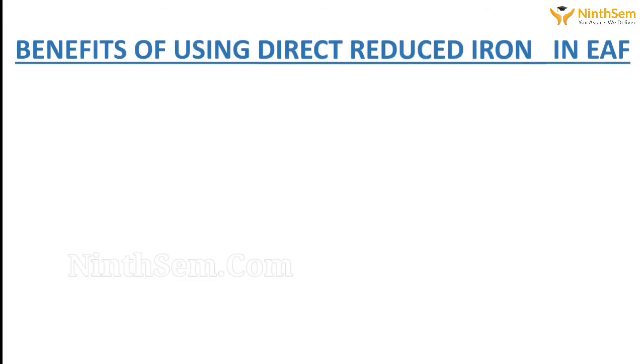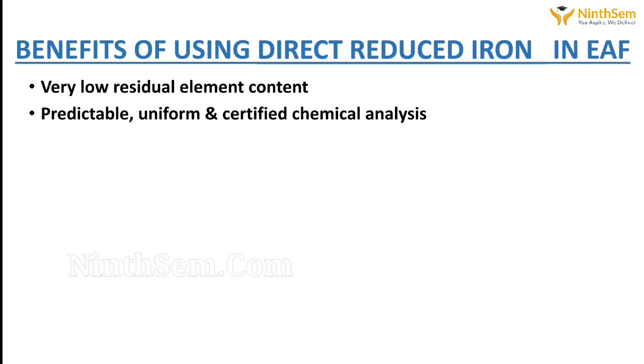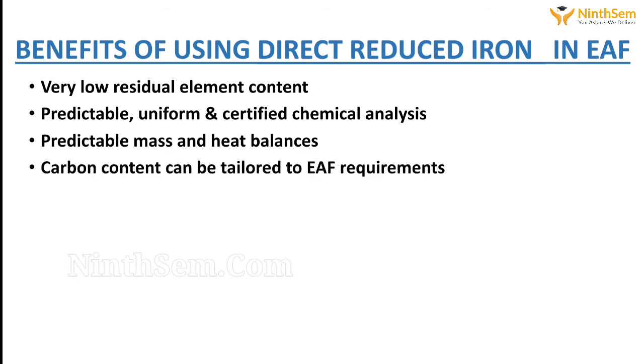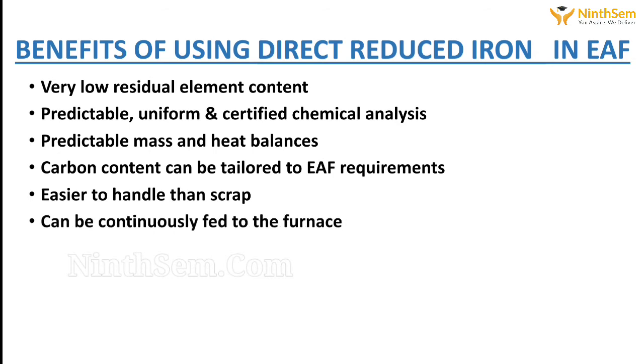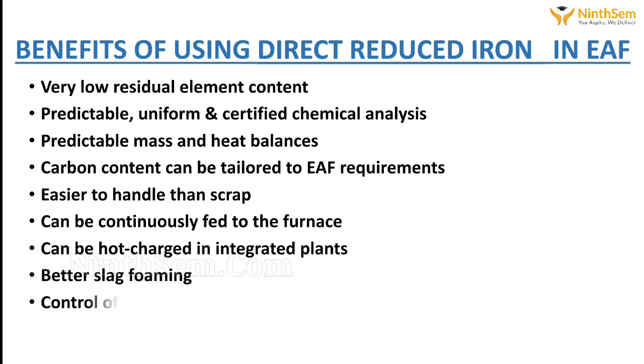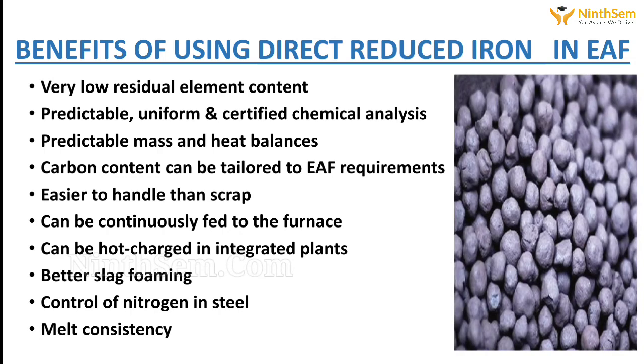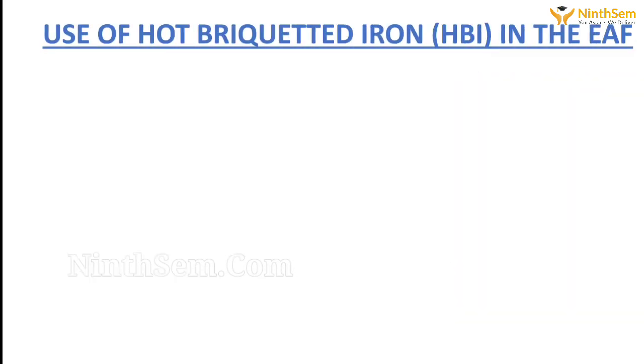Benefits of using DRI: very low residual element content, predictable uniform and certified chemical analysis, predictable mass and heat balances, carbon content can be tailored to electric arc furnace requirements, easier to handle than scrap, can be continuously fed to the furnace, can be hot charged in integrated plants, better slag foaming, control of nitrogen in steel, and melt consistency. Use of hot briquetted iron in the electric arc furnace.